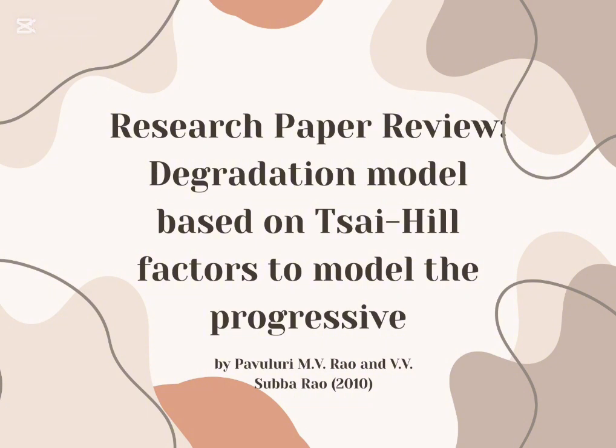Earlier degradation models often assume that once a layer fails, its stiffness instantly drops by a fixed percentage, say 50% or 100%. But this is an oversimplification, since in reality, stiffness doesn't drop uniformly. Some parts of the laminate continue to carry load even after local damage occurs. The authors therefore developed a new degradation model that links stiffness reduction directly to the Tsai-Hill failure factors, allowing the material properties to degrade progressively and realistically based on which part of the material is failing.